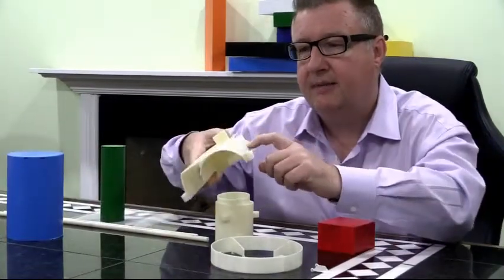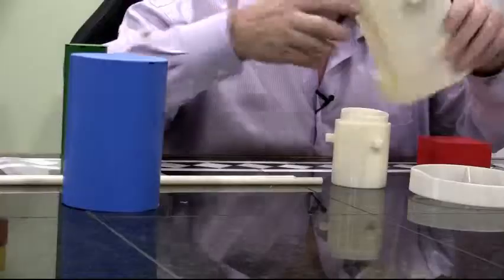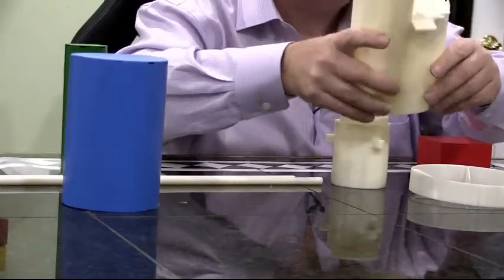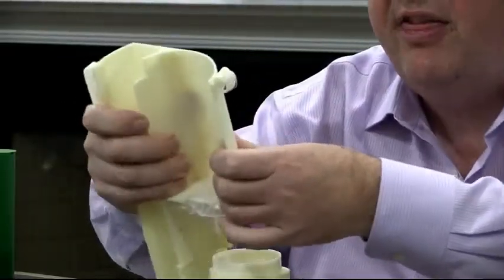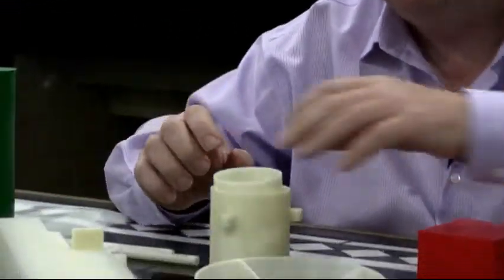You can see these layers in some parts. And if you want to try and use rapid prototyping to make parts, you have to make the walls quite thick. And even then, they're still flexible — and as you heard that little crack, they'll break along the layers very easily. And that's the problem with trying to take parts from rapid prototyping machines and use them in finished products.